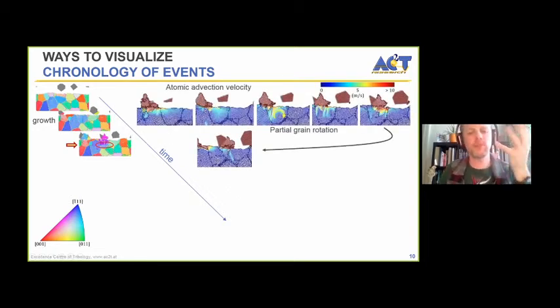So we flip into another view, we put on our augmented reality goggles, and we look at the atomic advection velocities in that system. So all the atoms are replaced now by little arrows showing where they want to go at the moment. And we're zooming in on the low velocities. Up here it's 80 meters per second, which is very fast. Down here, we're looking only at velocities between 0 and 10 meters per second, which is still fast tribologically, but if you're grinding across so fast, this is actually relatively slow.